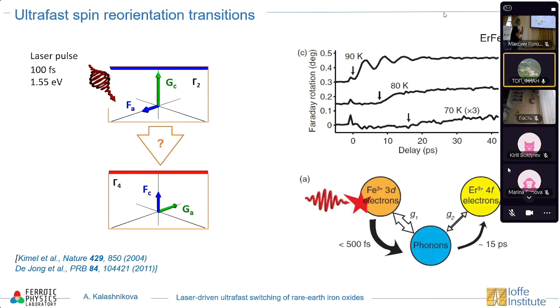And it was suggested that, in fact, the mechanism behind this transition is the following. Usually we use femtosecond laser pulses to excite the material, which are in the near infrared or visible range. Therefore, they are mostly absorbed by iron electrons. Then there is very fast relaxation and energy transfer to phonons. Basically, the lattice is heated up.